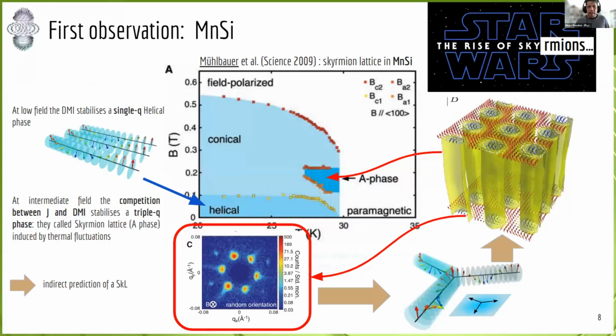Okay, but the real rise of the skyrmion was in 2009 with the first indirect observation of this texture in this compound, MnSi. Mühlbauer and company showed that in the phase diagram of temperature and magnetic field, they found a specific region where neutron scattering in the reciprocal space presents these characteristics, a triple-Q structure in the intensities, which is basically related with the superposition of three spirals in different directions, which is related with the presence of this skyrmion. This is why I say that this is an indirect observation.